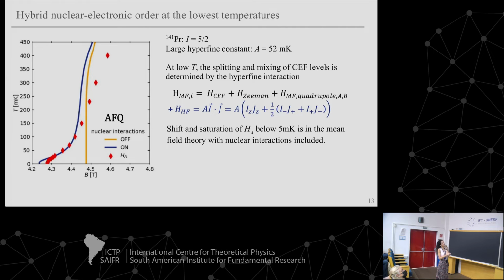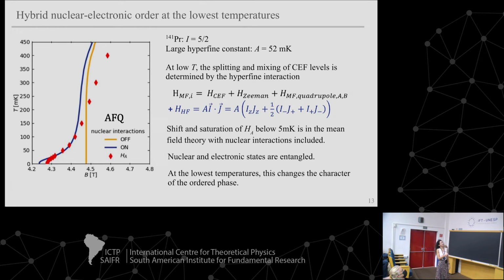So these are our data points that I showed you also on the previous slide. And quantitatively, the match is not good, but qualitatively, the shape of this phase boundary is very well matched to what we would predict by including just the hyperfine interactions in the mean field Hamiltonian. Also, this saturation below 5 millikelvin comes out of the theory as well. So we thought that this was a great match. We were very pleased with it. The other thing to think about is that at this low temperature, now inside this phase, the system down here is really quite different to up here.